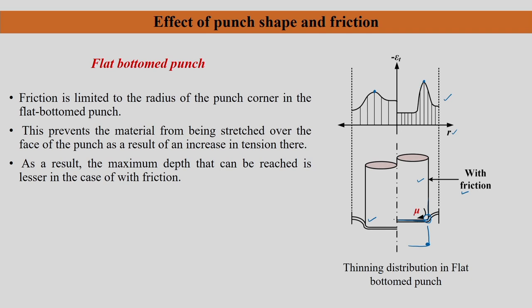So, naturally what you can do is, in the without friction case, you can go for a larger draw, larger stretching as compared to the with friction case. As a result, the maximum depth or forming height that can be reached is lesser in the case of with friction. That is why I just made this difference.